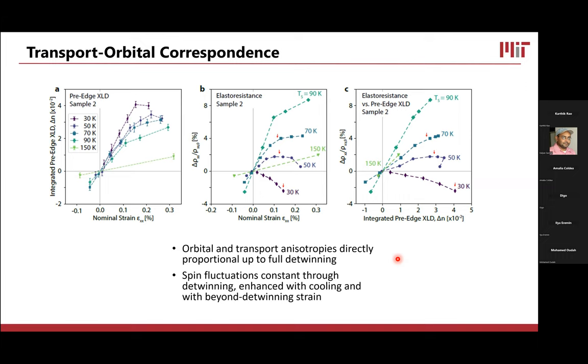But when I get past full detwinning, my orbital polarization stays saturated and I start to see other effects show up. Within that domain, since the slope is changing as a function of temperature, that would suggest that the way that the spin fluctuations are contributing to the resistivity anisotropy is changing as a function of temperature. That's my basic idea. So the reason that this is dropping, I'm going to say, is because the spin fluctuations are contributing a negative elastoresistivity that's continuing to diverge as you cool down towards zero Kelvin.